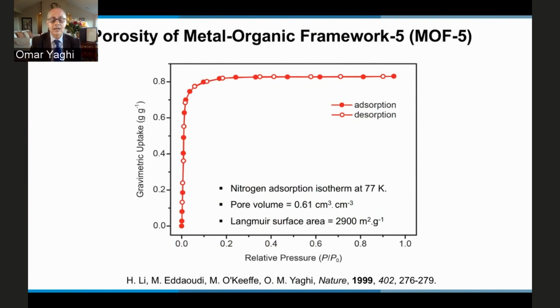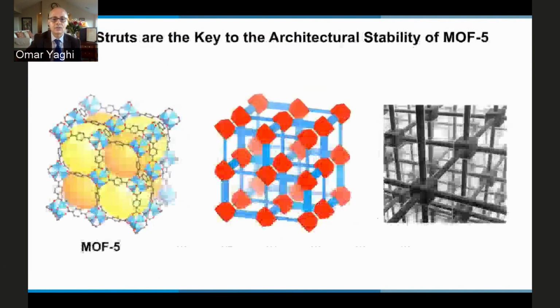So you see here the gas adsorption isotherm, a typical type 1 isotherm with a sharp knee, fully reversible, and it's done as the gold standard for porosity at 77 Kelvin and low pressure. So this set the field on an expansion course. The extremely high surface area broke all records of porosity, a record that had been held for 1,000 years by porous carbon. And now we have materials where, as I will show shortly, every atom is an adsorptive site.